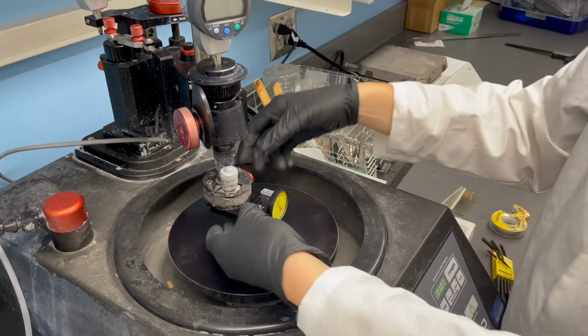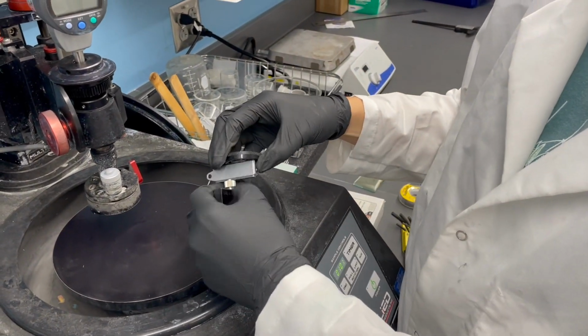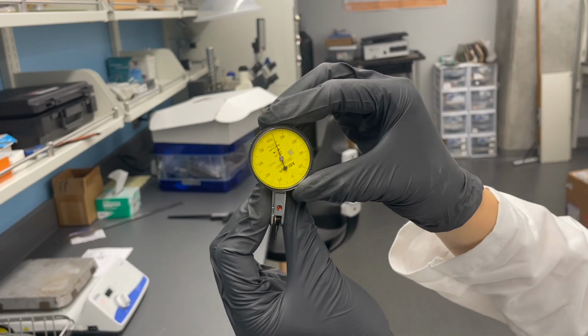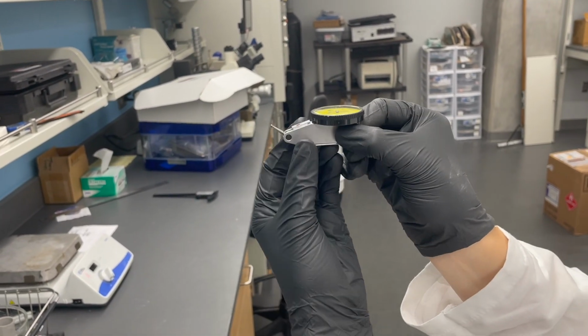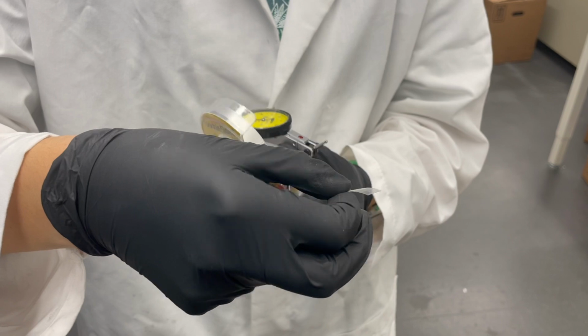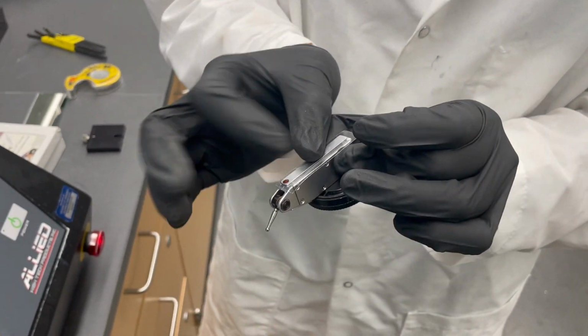Remove the calibration tool and take off the dial. Rotate the dial so that the needle points to 100. Flip the dial arm so that it is pointing 45 degrees upwards. Then attach double-sided tape to the bottom of the dial.